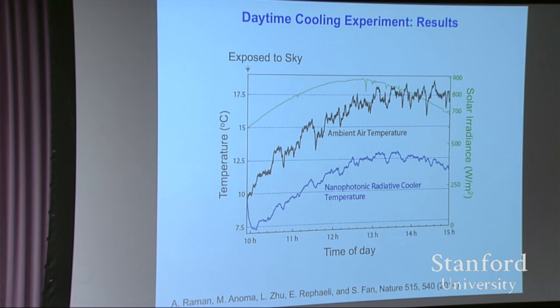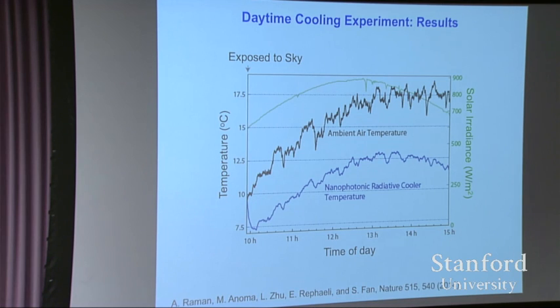You did this and you averaged the results over several days. Do you have the results we could see for that? I don't have it with me. Now, the result depends quite a bit on the air quality. And this was done actually in December of 2013. I showed both of these data, but on 2 separate days, so you can see actually the temperature is slightly different. Those few days happen to have a very low dew point, so the transparency of the air is particularly good, which we didn't know. We learned it later. That makes a huge difference. So this is a technology that does depend on the weather.